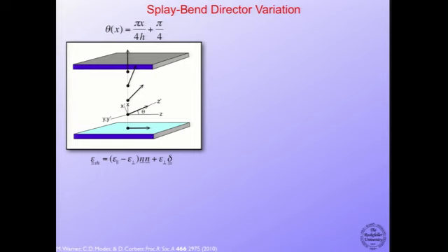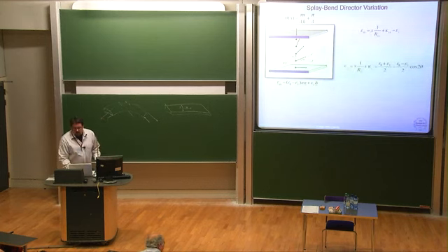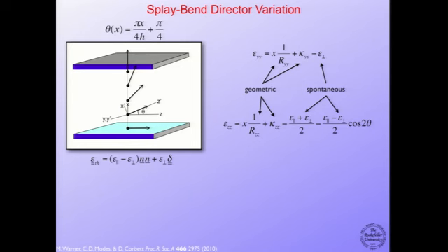You know that, so this is the spontaneous strain that's applied in the frame of the nematic director. You get the elongation, the strain parallel to the director is one thing, and the strain perpendicular to the director, the normal parts of the principal frame, is epsilon perpendicular. So you can write down the total strains, which have contributions from the geometry of the bend. So you imagine that you're in some partially bent state, and the spontaneous parts are just the rotations of this into the body frame.